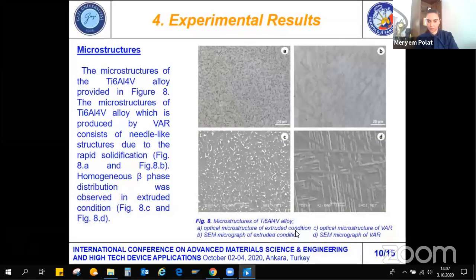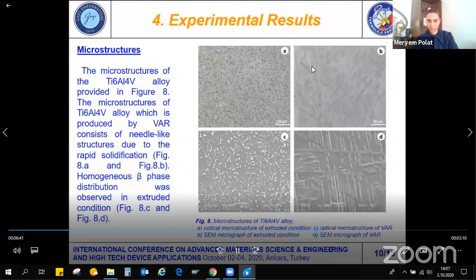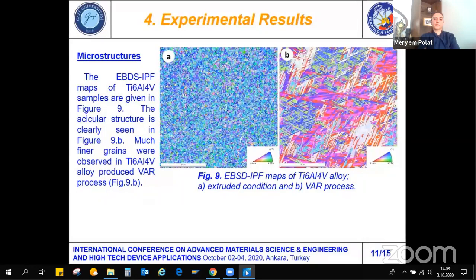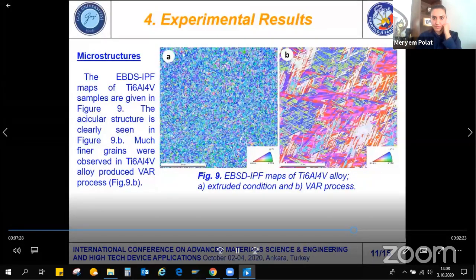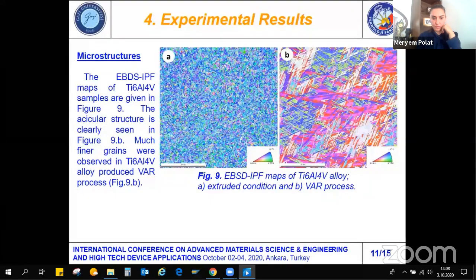The microstructure of titanium 6 aluminum 4 vanadium alloy is provided in figure 8. The microstructure of the alloy produced by vacuum arc remelting consists of needle-like structures due to the rapid solidification. Especially, you are seeing figure 8a and figure 8b. Homogeneous beta phase distribution was observed in the extruded condition, especially you are seeing figure 8c and d. The EBSD IPF maps of titanium 6 aluminum 4 vanadium samples are given in figure 9. The acicular structure is clearly seen in figure 9b. Much finer grains were observed in the alloy produced by the vacuum arc remelting process.